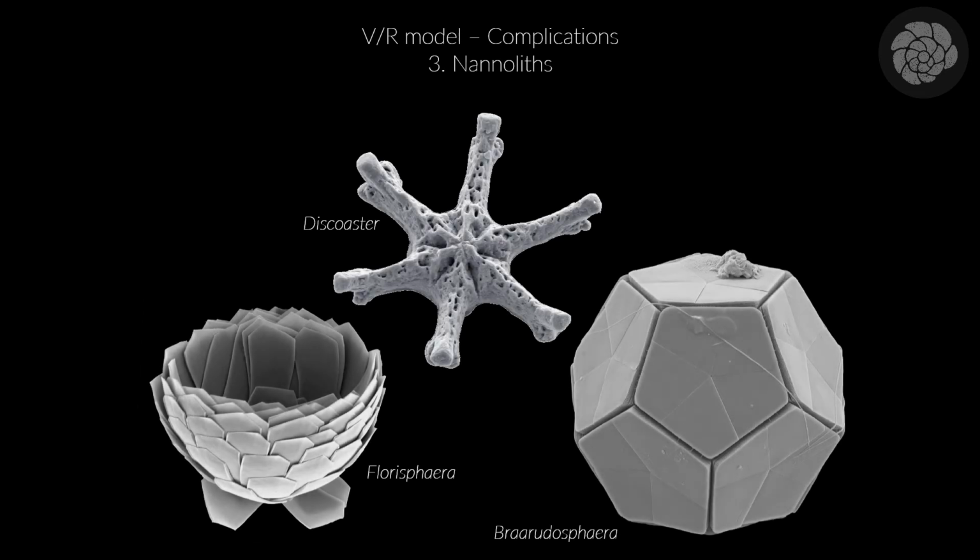Okay. Final complication, which I thought I should throw into this version of the talk, is nanoliths. So we've got holococcoliths, we've got heterococcoliths, both of which are produced by Coccolithus pelagicus, both of which are coccoliths, which we define as being things produced in a homologous way to the coccoliths formed by Coccolithus pelagicus, since that's the original one. But then nanoliths are calcareous nanofossils, the same size as coccoliths, showing complex regular structures right down to crystal level. But they don't show either VR mode calcification or holococcolith calcification. So they don't fit either pattern.